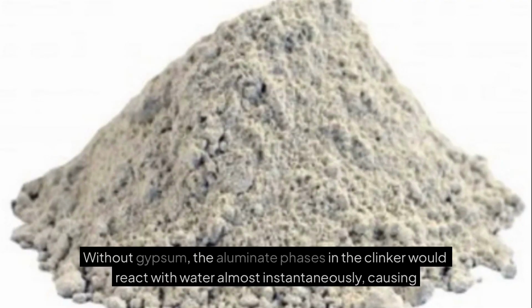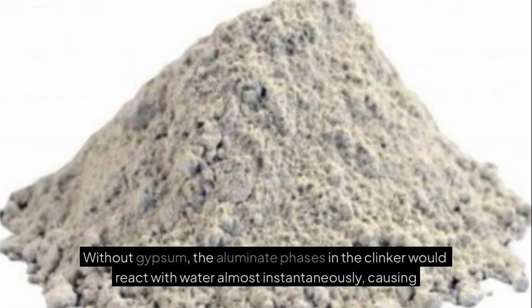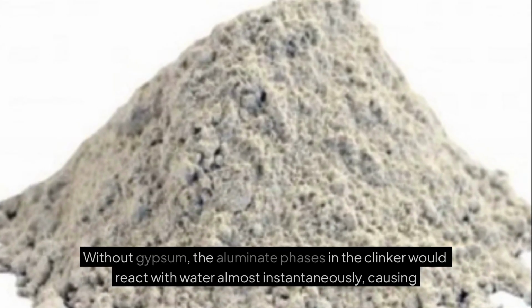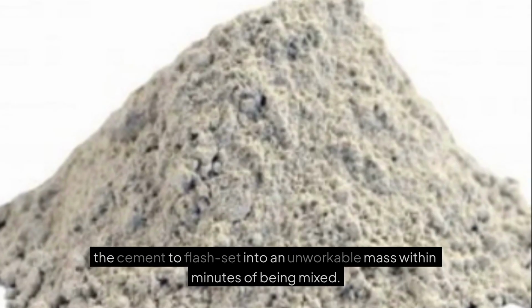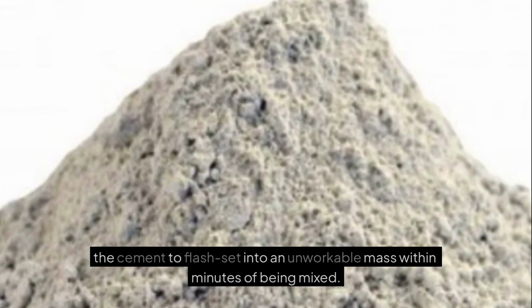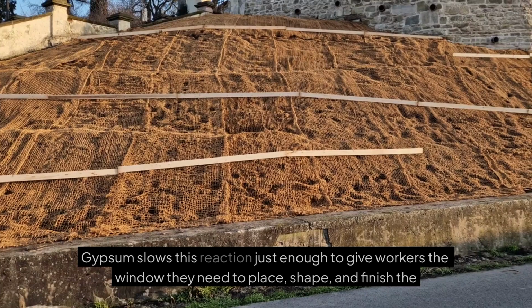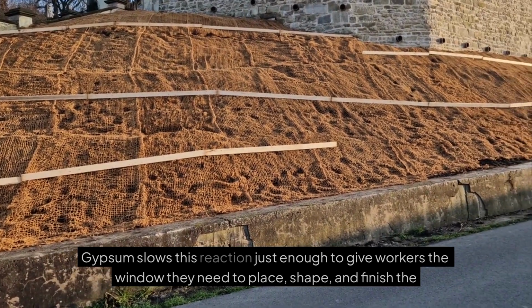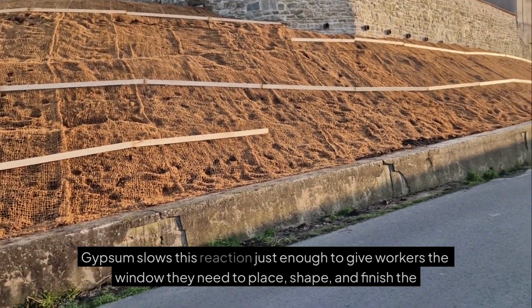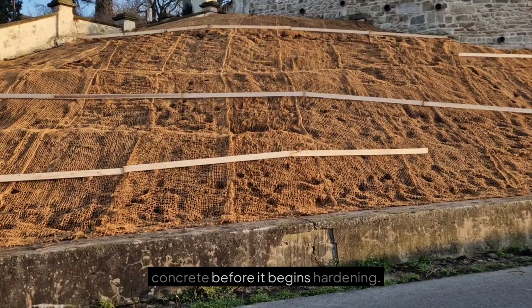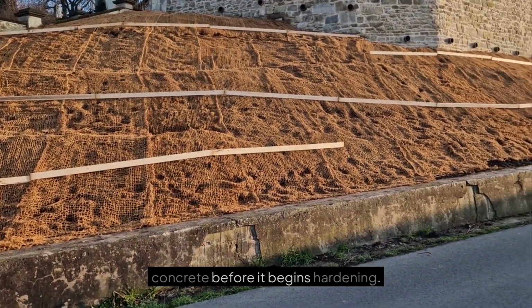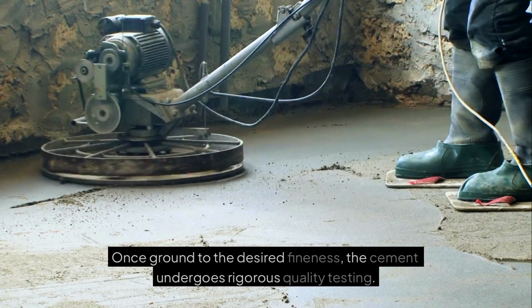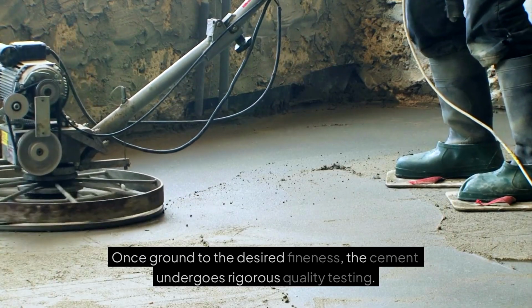Without gypsum, the aluminate phases in the clinker would react with water almost instantaneously, causing the cement to flash set into an unworkable mass within minutes of being mixed. Gypsum slows this reaction just enough to give workers the window they need to place, shape, and finish the concrete before it begins hardening. Once ground to the desired fineness, the cement undergoes rigorous quality testing.